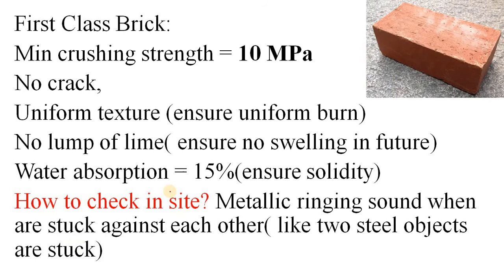First is the first class brick. First class brick looks like this: uniform in shape, reddish color, and very good uniform texture. The crushing strength is a minimum of 10 MPa. If the crushing strength is not 10 MPa or more, then it is not first class brick. Next point: there should not be any crack. If there is a crack, obviously during application of load it can split, so it doesn't qualify for first class brick.